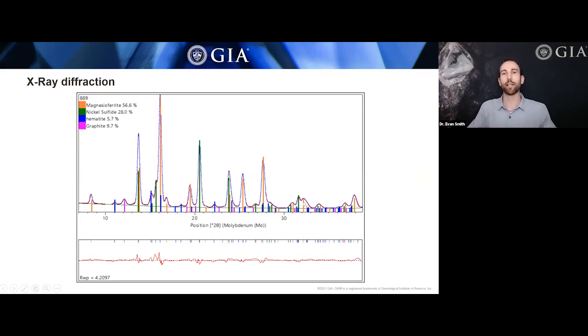So this is the diffraction pattern that we collected from that inclusion. And it contains multiple phases in it. And using some special software, we can try to identify all the different materials that are superimposed on this diffraction pattern. And it's mostly made up of a mineral called magnesioferrite. It's also got some hematite in it and graphite, but it also has this here, a nickel sulfide. And this is something that's in the database that I was comparing with, but it's not actually given a mineral name here because it's not actually a mineral in the database. This nickel sulfide that's in the database is alpha nickel sulfide.